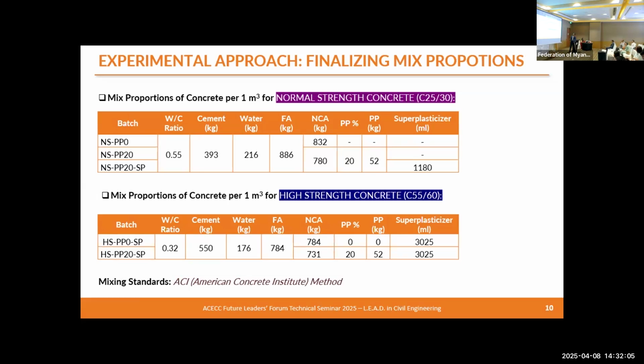When it comes to the high strength one, you know that it's really difficult to achieve the strength and the workability in high strength concrete without a superplasticizer. That's why for the normal mix as well as the plastic incorporated mix, for both we used the superplasticizer.